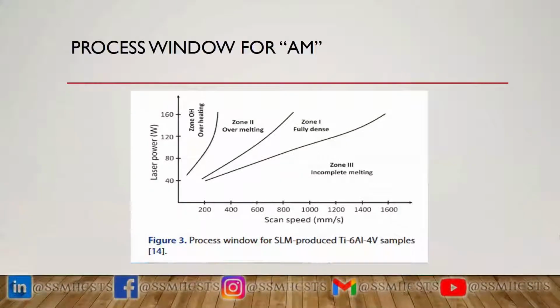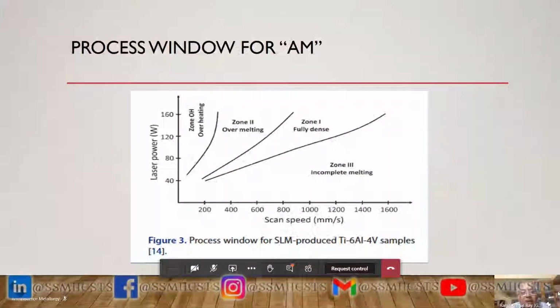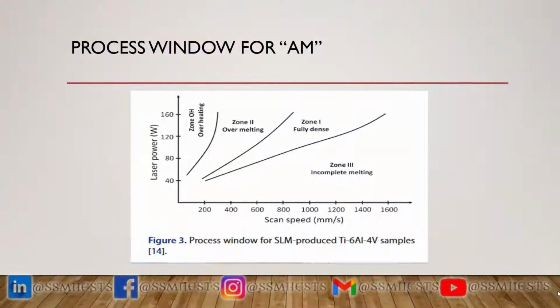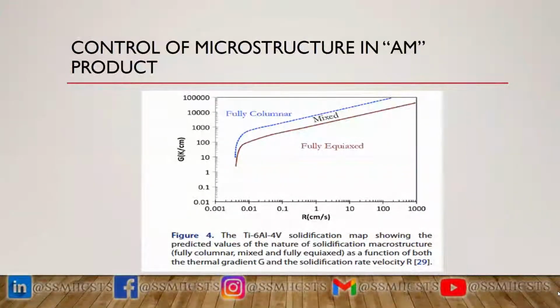Yeah, this shows that you can easily find out the process window necessary. So if you want to have fully dense material, you choose, this is for the selective laser melted process, laser power and scan speed. So the processing window can be found out by trial and error method. Can I have the next, please? Yeah. Again, you can control the microstructure by controlling parameters like the thermal gradient and the solidification rate velocity. Next one, please.